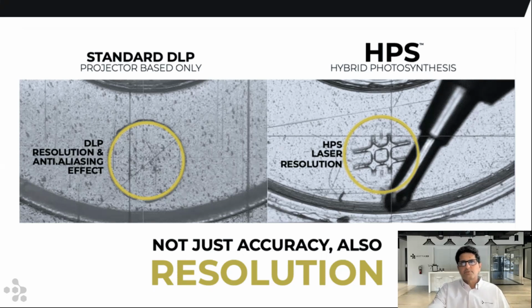Resolution, once again, if you see the difference between the left and the right, because of pixelation and whatnot, on a pure DLP projector-based system, it's a hit and a miss based on where the position of that high resolution feature lies. In our case, these are done by the lasers, so they're never missed, they're accurate, and they are to spec almost in all cases.